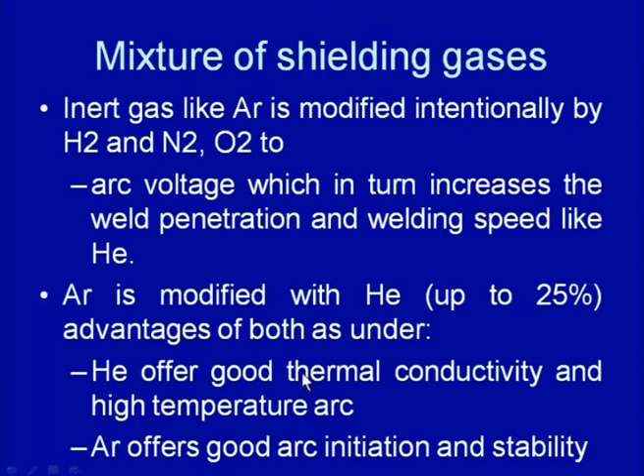Argon also offers advantages such as better arc initiation and arc stability. When a mixture of both helium and argon is used, that mixture provides the positive points of both gases. It is common to use argon-helium mixtures where helium content can vary up to 25 percent to take advantage of helium.